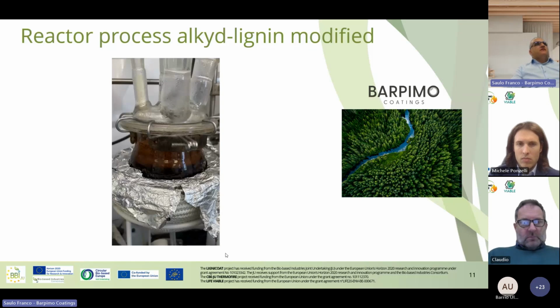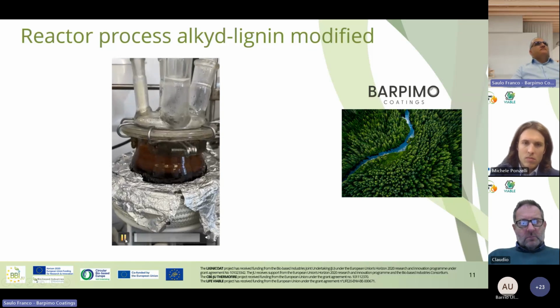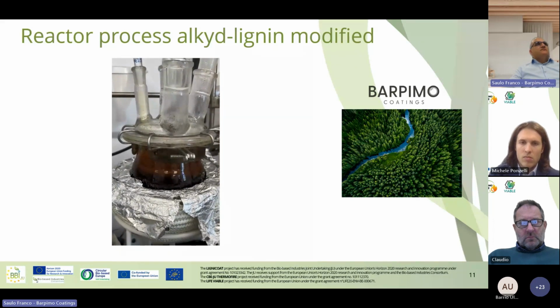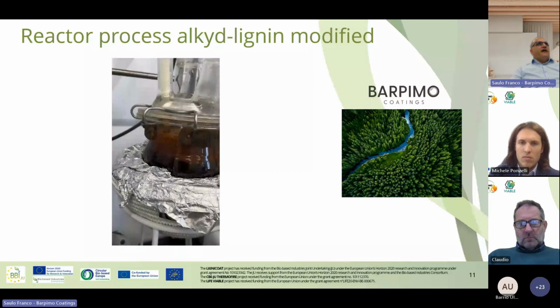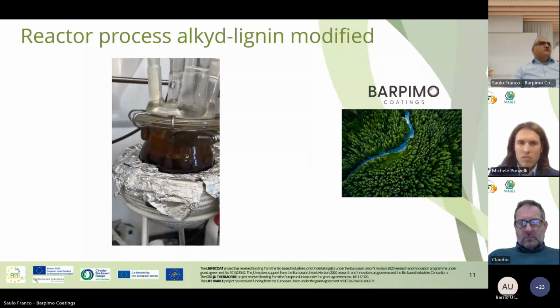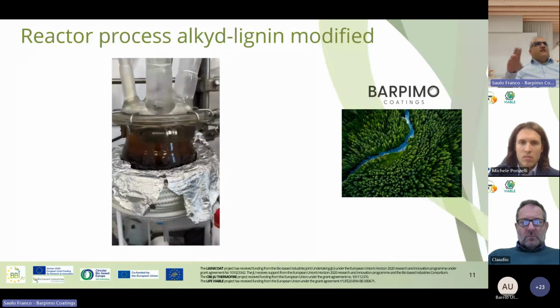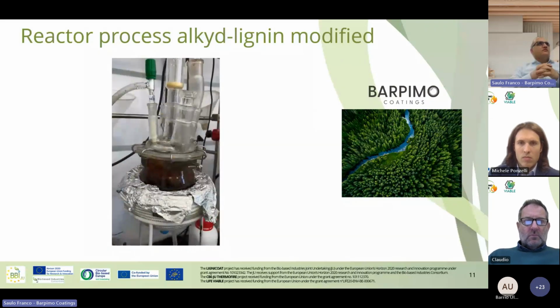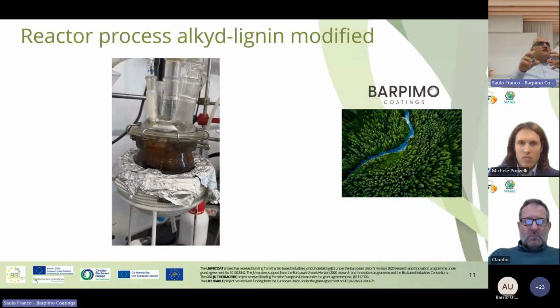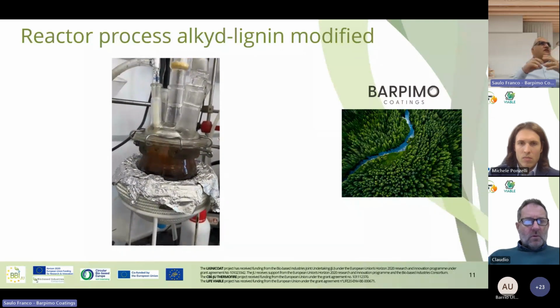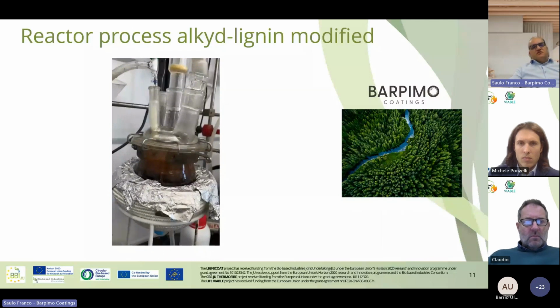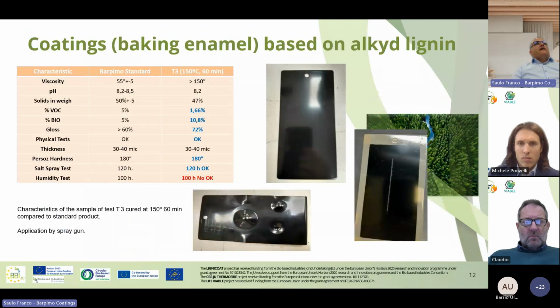Well, and here we have another video in the production of the alkyd. As you can see, the reactor, you have performance, no gelling or particles undissolved, or sometimes some raw materials cause a lot of foam. So in this case, the performance of the lignin in the reactor was correct. And then we performed bake enamel based on alkyd lignin resin.